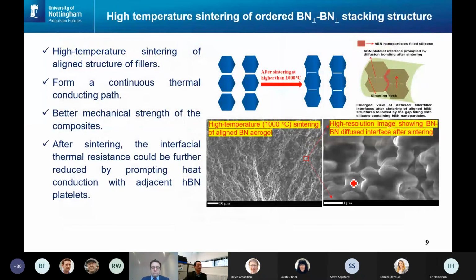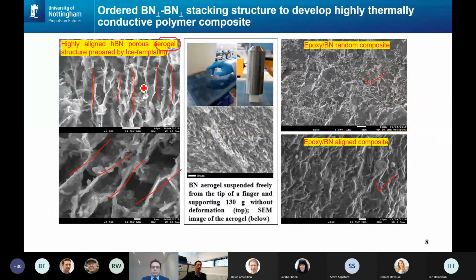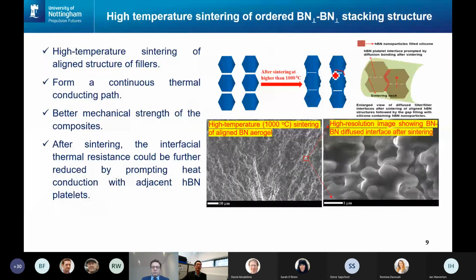One of the methods we can think of is to do a little bit of sintering. If we sinter this porous aerogel structure, we try to link the interface, this boundary, more strongly or more solidly, because at this temperature interfacial diffusion happens there. Then we link the boron nitride platelets together, and that will increase thermal conductivity significantly.